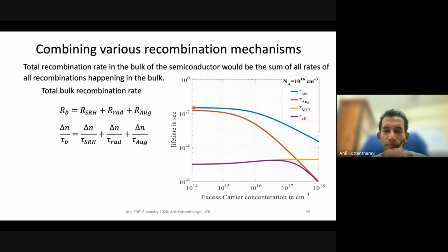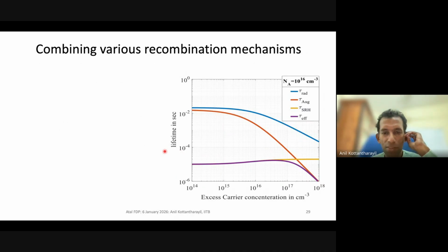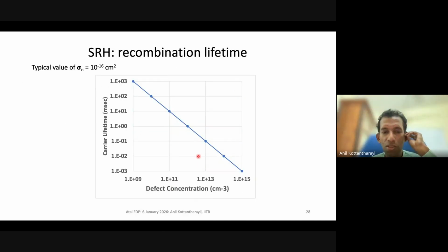You can see here the radiative recombination lifetime is high, and it is determined essentially by the properties of the material, so we don't have much control on this. Auger recombination is also effectively decided by the material properties. What is in our control is the SRH recombination, which is dependent on the defect density in the semiconductor. You can see that as the defect concentration increases, the carrier lifetime decreases. So you need to make higher and higher purity material, and in fact that is one of the things that has been happening in the PV industry. For example, till 2006 or so, the PV industry was very small, and they used to use wafers rejected by the IC manufacturers.